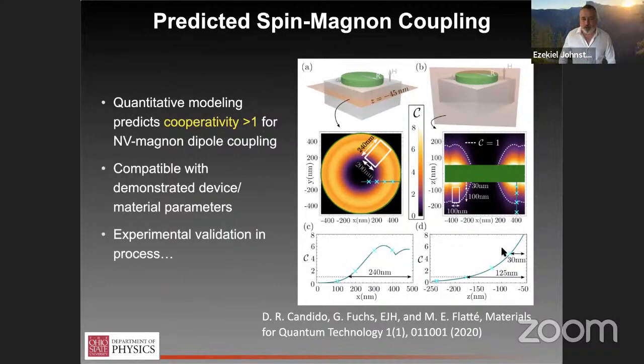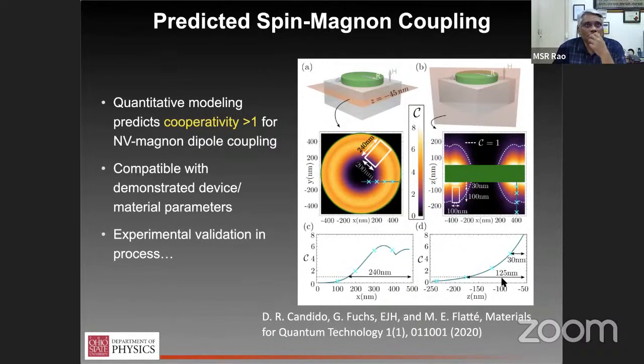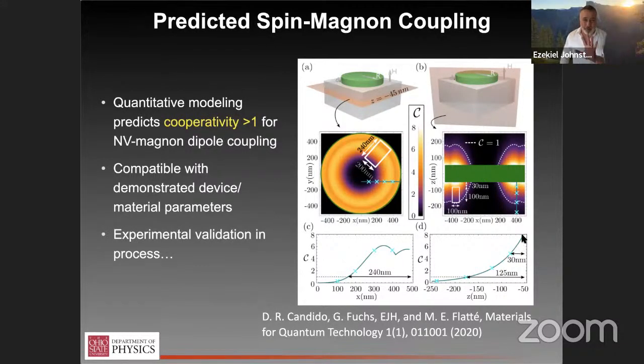Okay. And so, we picked 30 nanometers as sort of our design parameter because from the NV community, this is the depth at which you stop being particularly sensitive to surface spins. Okay. But in principle, up to over 100 nanometers. So I will say, to be fair, this is a theory paper, predicting optimal performance. So this is assuming that one has optimal NV coherence times, right? Which for people working in the field, I don't have to say that's not very easy to do at all. There's only a handful of groups that have demonstrated the ability to get coherence times that long.